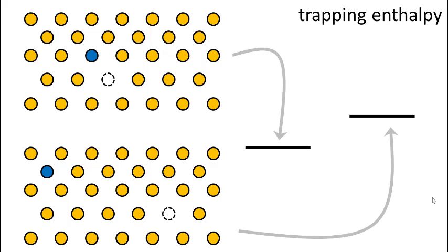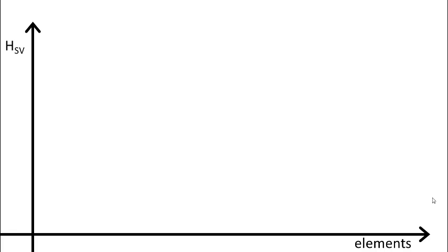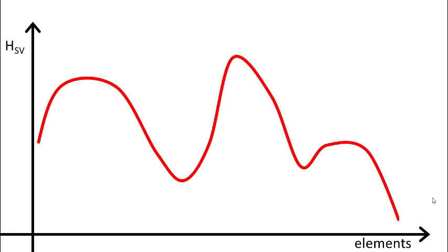The energy of the system with a vacancy trapped by the impurity will often be lower. And the energy difference between both, that is this trapping enthalpy. I will now plot first in a cartoon and later with real data, I will plot this trapping enthalpy as a function of the impurity element. And my cartoon looks like this. We will reason first about the cartoon and then it is straightforward to understand the real data.